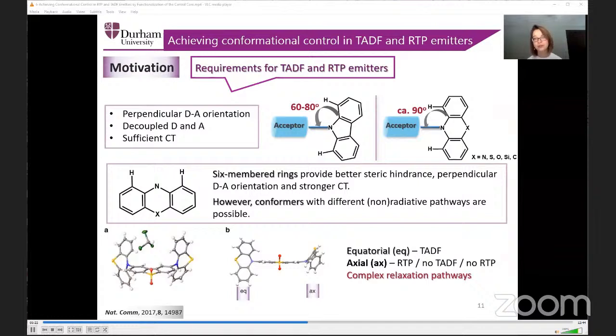However, if we take a small donor such as carbazole and link it orthogonally to the acceptor, we will not be able to ensure orthogonal orientation, because the donor does not provide sufficient steric hindrance and it would rotate freely around the donor-acceptor bond. That would lead to the lack of charge transfer character and cancel TADF in this case. Therefore, to ensure strong charge transfer, we tend to utilize six-membered ring donors such as phenothiazine and acridine. While those enable stronger charge transfer character, they might also lead to the observation of various radiative and non-radiative pathways.